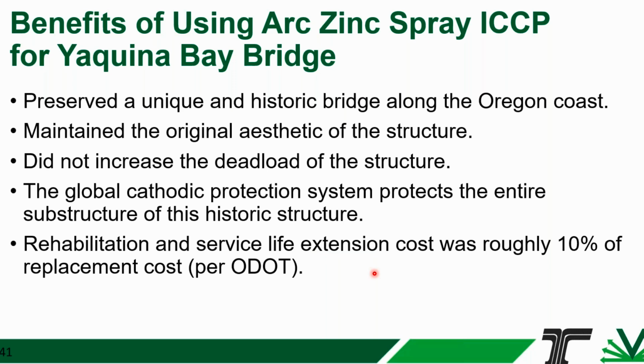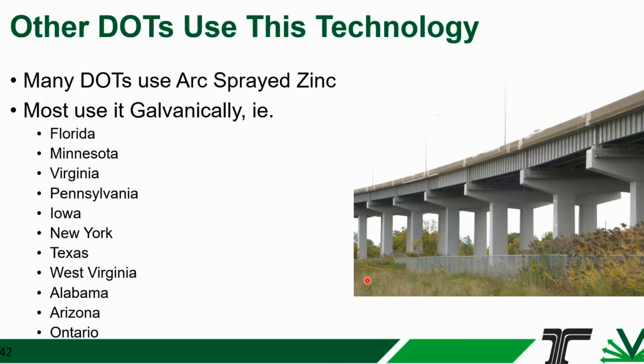Now, many other DOTs are using arc sprayed zinc or arc sprayed aluminum alloys in different ways. As Ray mentioned, California did the original work with impressed current. Oregon has done by far the most with impressed current arc sprayed zinc. A few other locations have done some as well. A lot of states are using arc sprayed zinc and using it galvanically, which is simpler to install and less upfront cost, but it doesn't have some of the advantages that the impressed current option does provide.